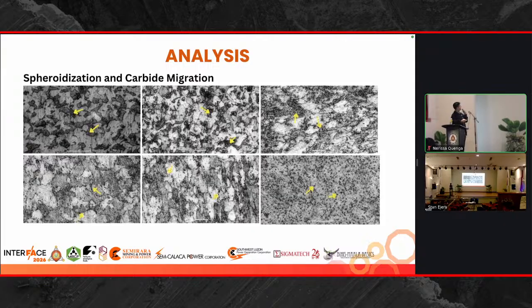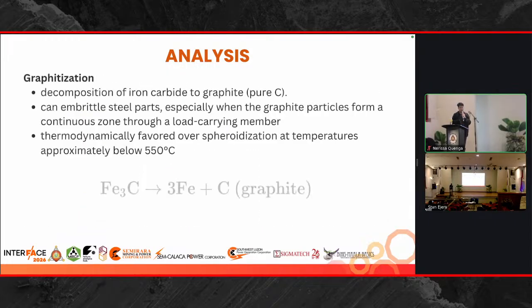Yeah, so these are just the carbides. And next is graphitization, another degradation mechanism, which is the decomposition of carbides into iron and carbon, which is the graphite. The presence of graphites in the microstructure can embrittle steel parts, especially when graphite particles form a continuous zone through a load carrying member.